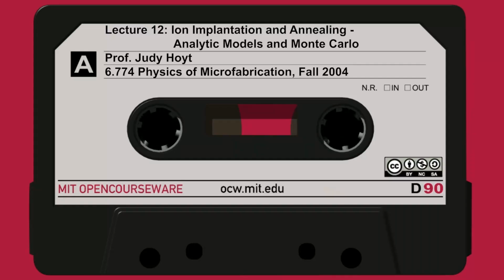As the current flows into the wafer, you can measure the current with an ammeter very accurately, and then you can integrate it over time. So you start the implant, opening up a shutter, and then you integrate over time. Each charge that comes in gets counted, and then you stop. So you can do this very, very precisely, because it's based on charge counting techniques, not on some chemistry of pushing a wafer into a hot furnace, hoping the temperature's right. Oh, you pushed it for 10 seconds too long. What? Pull it out. It's more of a physics-based approach.